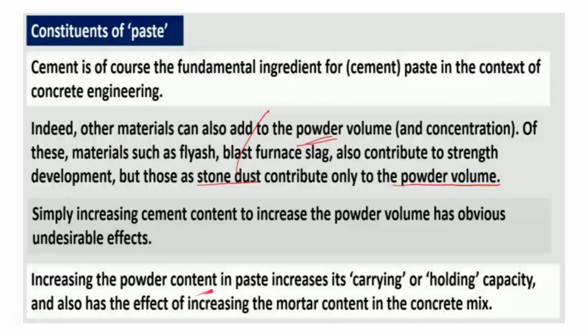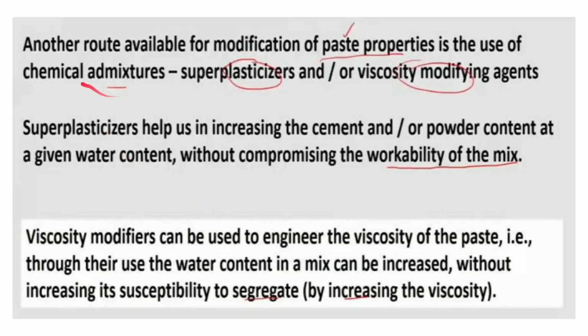Increasing the powder content in paste increases its carrying or holding capacity, and also has the effect of increasing the mortar content in the concrete mix. So if the criteria of this cement is satisfied, then the powder content increase in the paste will definitely increase the carrying or holding capacity, and it also increases the mortar content. Definitely, if this is increased, the mortar content will also increase.